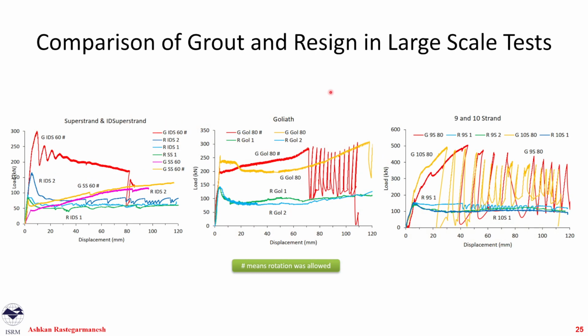Comparison of the grout and resin in large scale tests, as we can see, the difference is very easy to see. So our resin values are much lower compared to our grout values, which are the ones with G. And so it's very easy to see that our resin in this study was much different, and we didn't have the post-peak behavior where we see the oscillations.